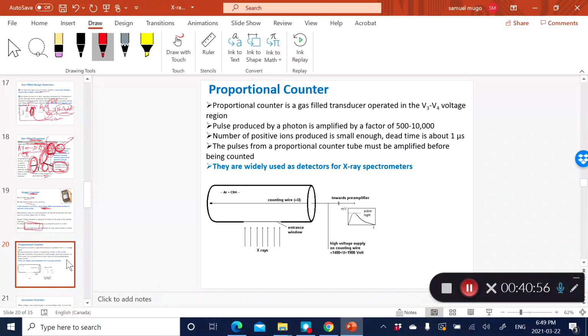Now, if you're in the middle region, up here, the linear region, where the voltage is just enough to cause a lot of amplification of electrons, however, not large enough to induce electrostatic repulsion or the space charge effect, then what you refer to is a proportional counter detector. And in this case, you can see the amplification factor is fairly big. It tends not to have a lot of dead time, because you're not getting the space charge effect taking over. And for that reason, it's a very widely used X-ray type of detector.